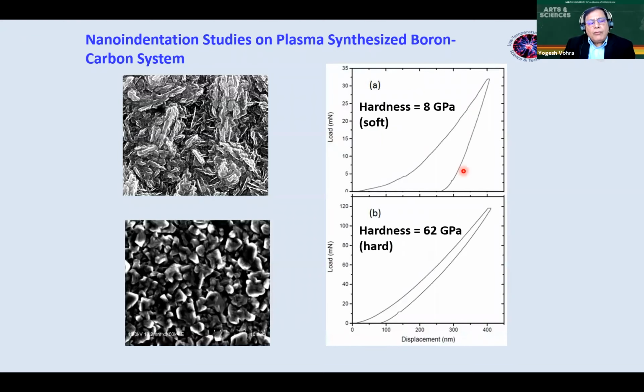So experimentally, what we found was that we can generate 2 types of morphology in our experiments. One of them, we measured the hardness, what we call a soft. The hardness is about 8 gigapascals. So soft is a relative term here. This hardness is much greater than most of the hard metals, you know.